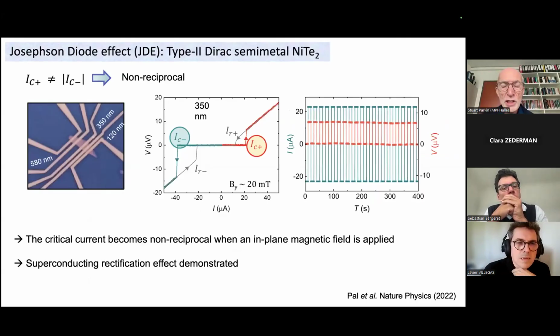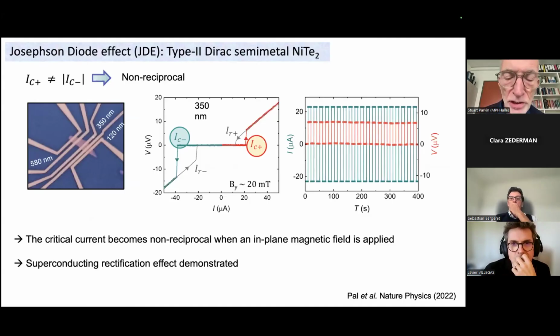So the most important point is what happens now when we apply the magnetic field. Now, we have to apply the magnetic field not parallel to the supercurrent, but perpendicular to the supercurrent. When we apply this magnetic field By perpendicular to the supercurrent, here it's 20 millitesla, now you can see that IC plus and IC minus take very different values. And here they differ by 40%. This is the device with a spacing of 350 nanometers.